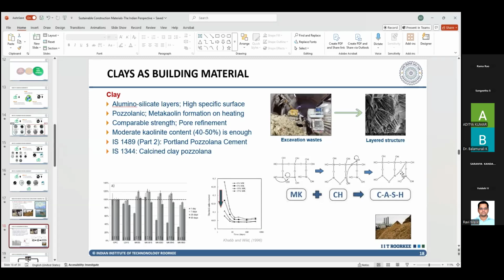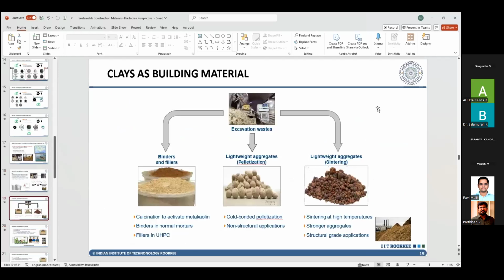This metakaolin has reactive aluminates and silicates which can react with the calcium hydroxide that is generated from cement when water is added to cement, which is basically a pozzolanic reaction. Even fly ash works the same way. Fly ash plus calcium hydroxide gives you C-A-S-H, or calcium aluminate silicate hydrates, which are the binding entity in concrete. So with that idea, we developed binders and fillers out of this excavation waste. We also developed pellets, which were used as lightweight aggregates for structural and non-structural applications.